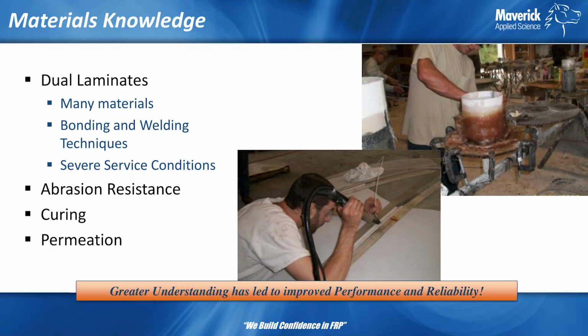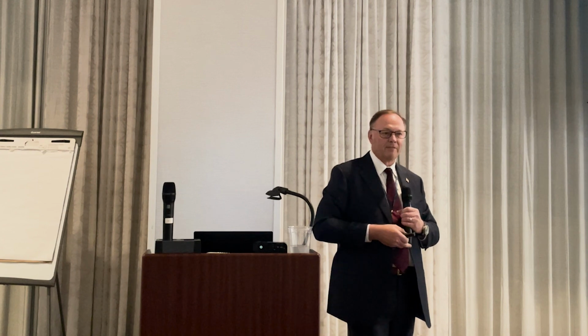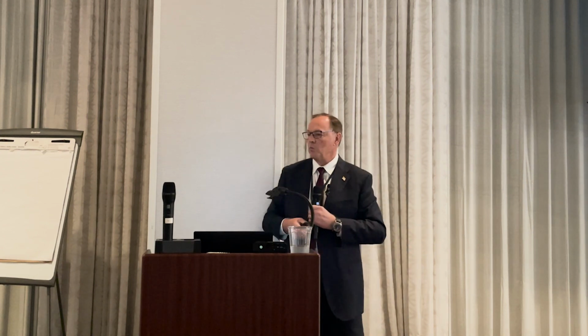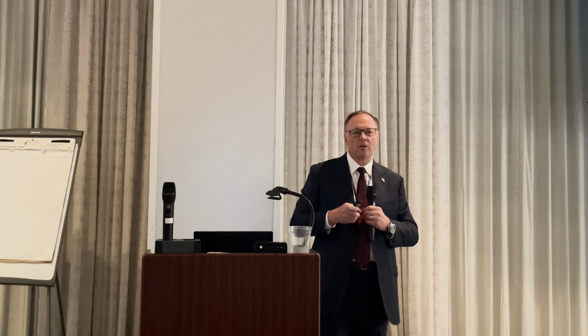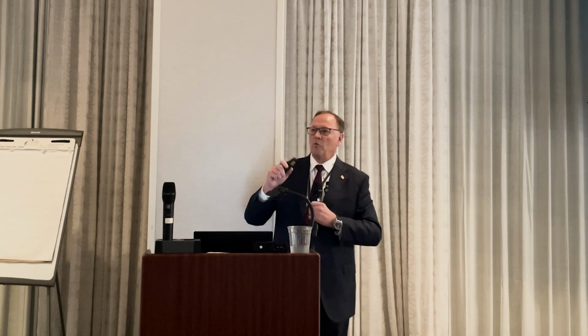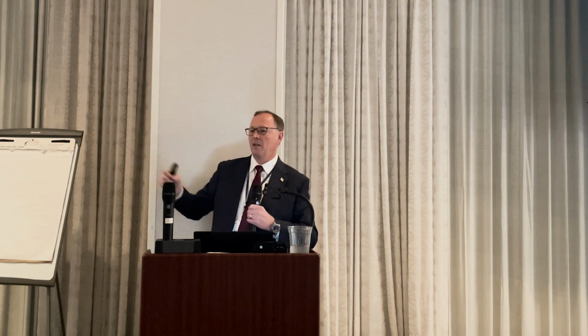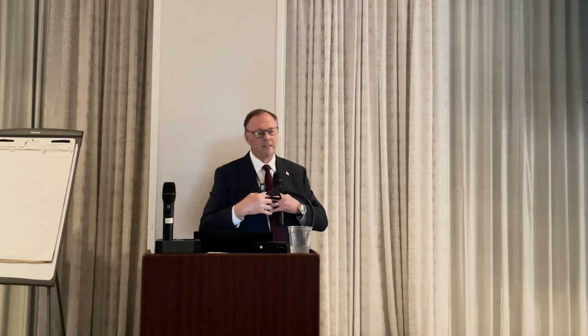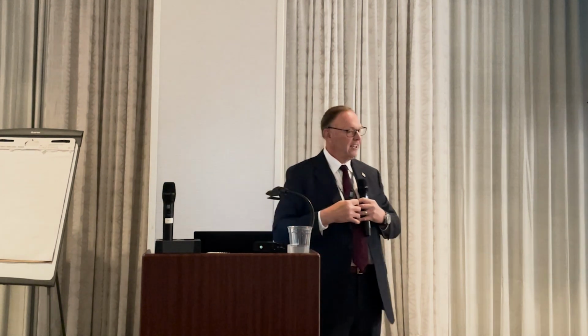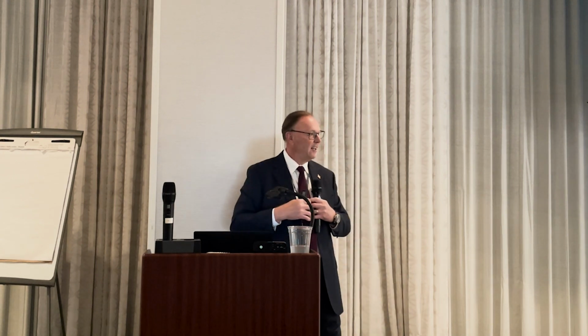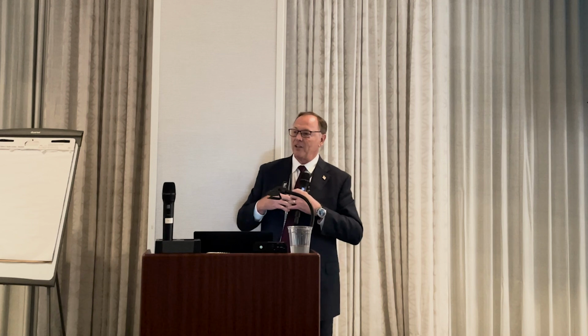Curing is a big point that we've learned quite a bit about. Generally, post-curing takes more time, and it's more expensive. Time is money, right? But what we've also found out, where surfaces are critical, if we post-cure it, we will move the mechanical properties from, say, 90, 93 percent to 100 percent. We will drive the cure. If you talk to Lisa here, she'll tell you all about cross-linking and stuff like that. And basically it drives that cure, so you maximize your mechanical properties, and you also maximize the hardness and your corrosion resistance as well.